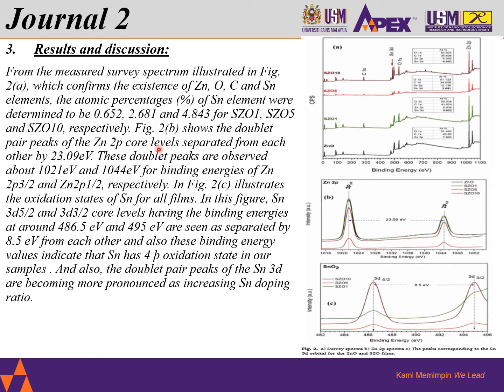Now the results and discussion. The measured survey spectrum illustrated in figure 2a, which is this one, confirms the existence of zinc, oxygen, carbon and tin elements. The atomic percentage of tin was determined to be 0.652, 2.681 and 4.843 for SZO1, SZO5 and SZO10 respectively. Figure 2b shows the doublet peaks of the zinc 2p core levels separated from each other by 23.09 electron volt. These doublet peaks are observed at about 1021 electron volt and 1044 electron volt, the binding energies of zinc 2p 3/2 and zinc 2p 1/2